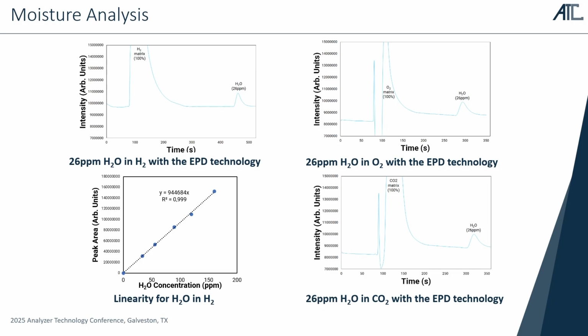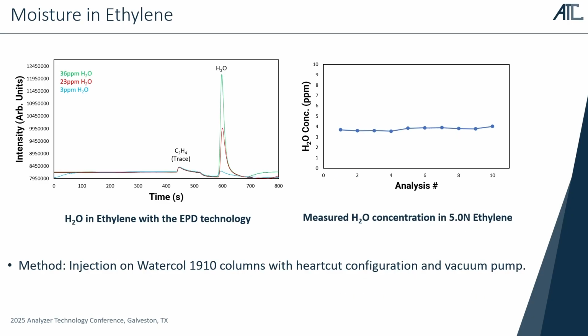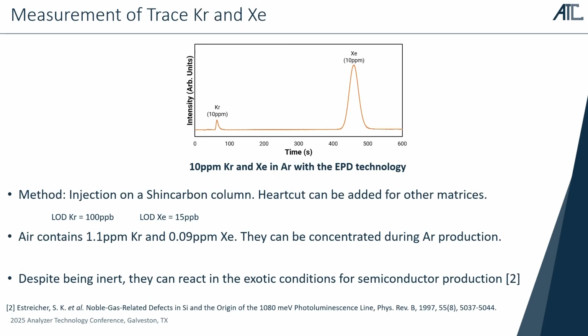Here are other examples of matrices that were tested for moisture analysis. So here, hydrogen and also oxygen and nitrogen and CO2 were tested. And we even tested this method with ethylene, and it's a very interesting method for measuring trace moisture in petroleum mixtures. We also tested some noble gases like krypton and xenon, and we can reach 15 ppb limits of detection for xenon and 100 ppb for krypton, which can be an interesting application for the air separation industry, as these two gases can accumulate in the argon production.